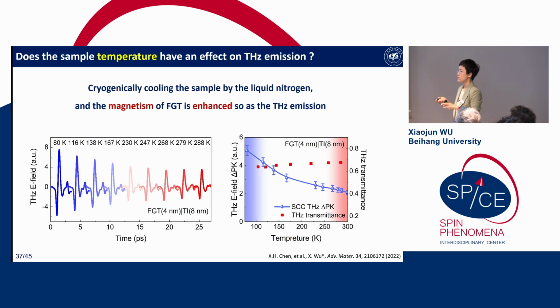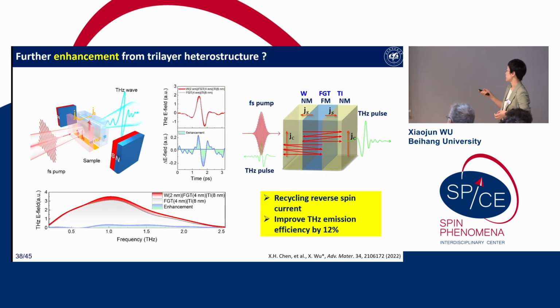But if we further cryogenically cool this sample with liquid nitrogen, the magnetism of this 2D magnetic material will be enhanced. So the topological insulator assists the terahertz radiation at room temperature, and the cryogenic cooling can also enhance the magnetization. So you can expect that the terahertz radiation intensity will be enhanced at low temperature. And you can also attach the topological insulator on this, and you can get some enhanced terahertz radiation. So that is why we choose 2D materials for terahertz.